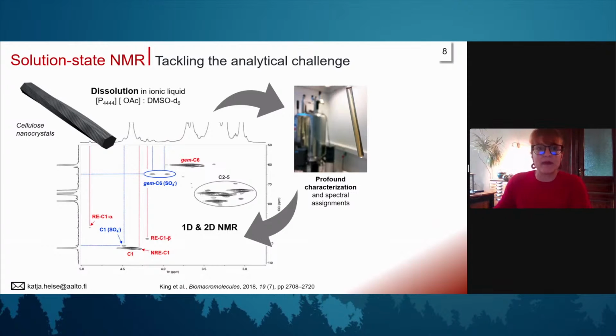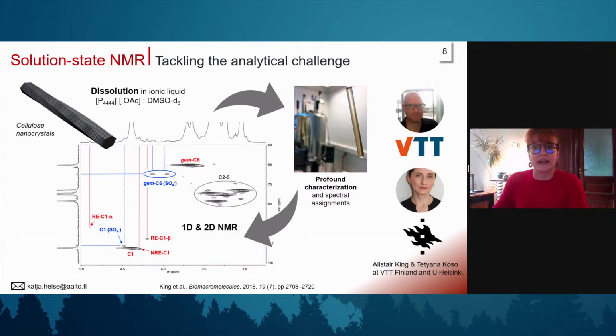It's a method that was published for the first time in 2018. The experts behind this are, of course, Alistair King, who is now at VTT, and also Tetyana Koso at the University of Helsinki. They have developed a method where they use an ionic liquid electrolyte with DMSO as a co-solvent to dissolve cellulose nanocrystals, and then carry out high resolution 1D and 2D NMR spectroscopy. And what I can tell you is that the resolution is good enough for even observing and confirming modifications at the reducing end groups, with this low abundance of newly introduced functionalities.